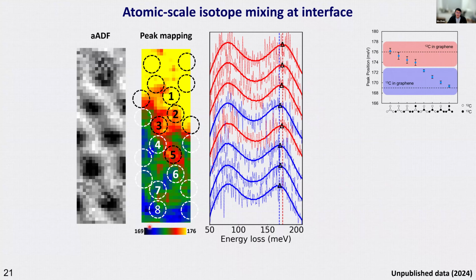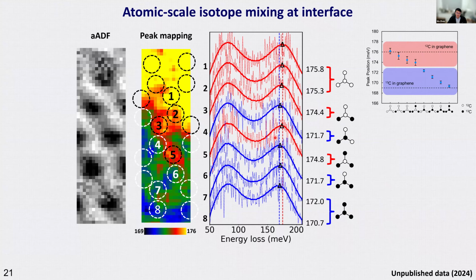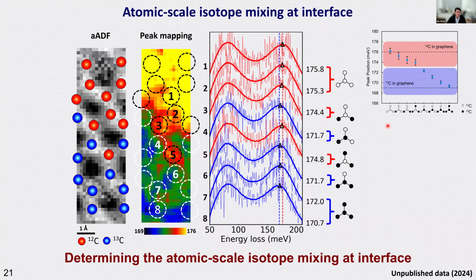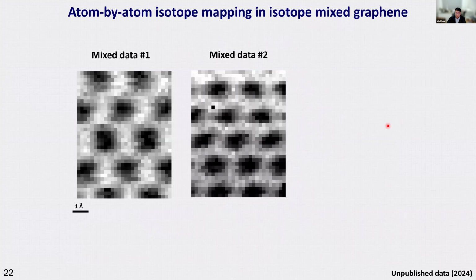And you can see that from the raw data and also from the denoised data, where we identify the position and assign it to different configurations based on the DFT calculated position. So in this way, we demonstrate that we can identify individual carbon atoms in the carbon graphene lattice with its isotope identity.